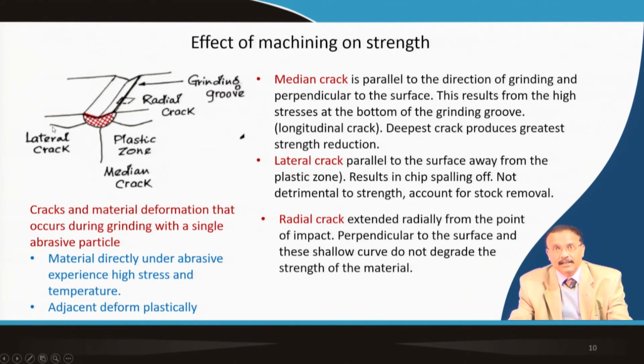Lateral crack, as you can see, is parallel to the surface which is being machined, and this results in the chip spalling off. It is not very detrimental for the strength of the ceramic article, but it is required for the removal of the material. Apart from this, you have a radial crack that extends radially from the point of impact, and it is also perpendicular to the surface. These kinds of cracks are not very deep. They are shallow and they do not really degrade the strength of the material.